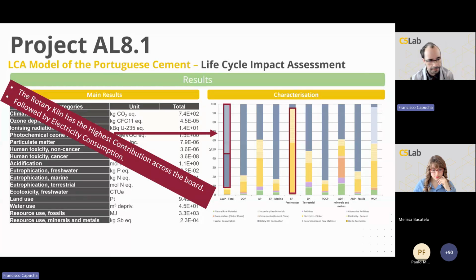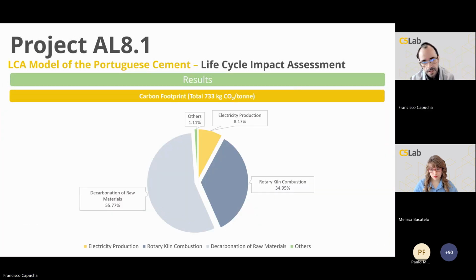This was then followed by electricity consumption, which is also highly relevant in some categories, such as freshwater eutrophication or acidification, concluding that energy consumption, together with calcining, is the major contributor to the cement environmental profile. This is further supported by the carbon footprint, where it's clear that the activity in the rotary kiln, so the fuel combustion and the calcining reaction, has by far the highest contribution, followed by electricity consumption, with all remaining processes contributing only around 1%.